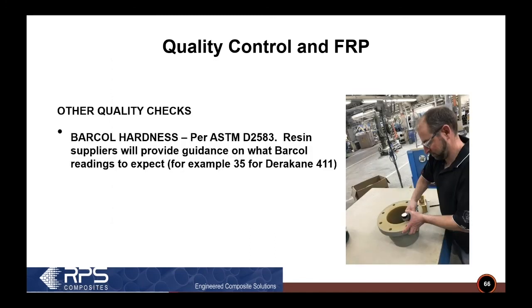There is also an ASTM standard 2583 that explains how a Barcol test can be used to check the hardness of the fitting, which kind of gives you an idea of the cure. The resin manufacturers actually tell us what the numbers should be. So for example, 35 is the number we're looking for with Derakane 411.